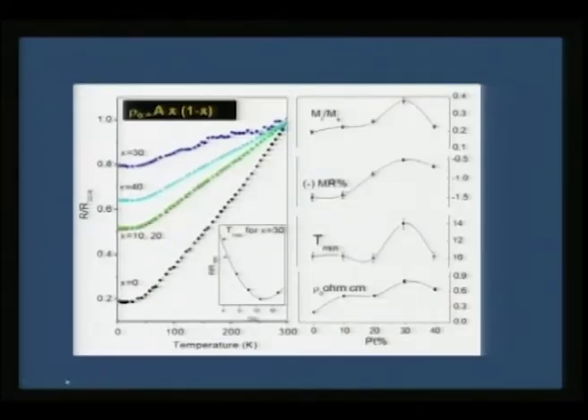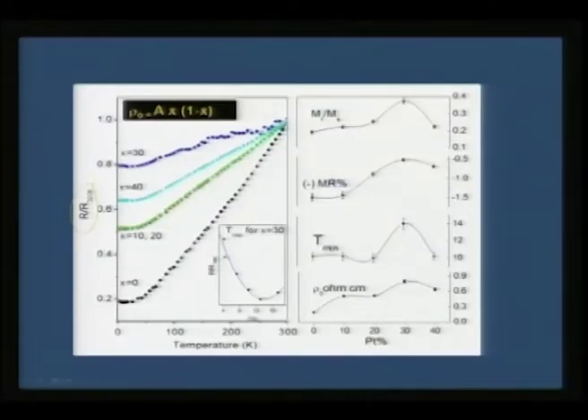Now one of the important things that I want to drive home in this view graph is what really happens to the electrical property in this sort of materials, nanomaterials. If you do the normalized resistance versus temperature plot, you can see systematically the resistance is increasing as you increase platinum. But what happens in all cases, you have a minima which is important from the physics point of view. This is exactly due to the local disorder or due to the magnon effect, and as a result you have an upturn in the resistivity below this minima.